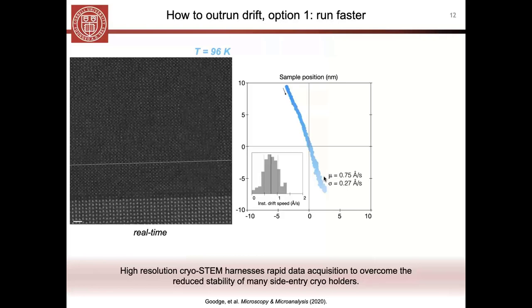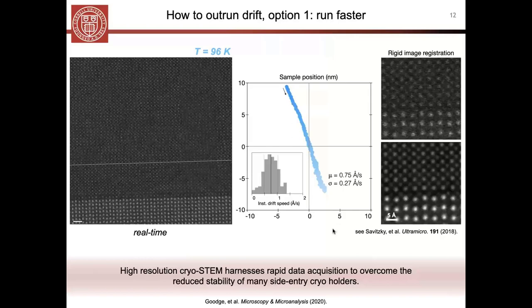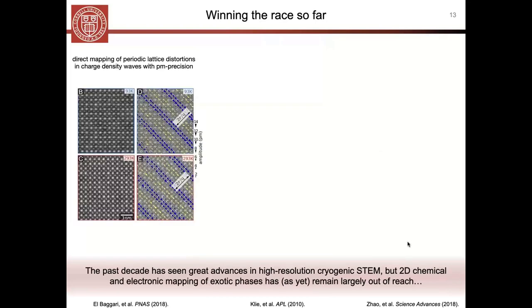Now, for relatively fast imaging techniques like, in particular, high resolution TEM or high resolution STEM, one way around this drift is to acquire a series of very, very fast images, like a stack of fast acquisitions, and then sum them together to produce a high signal to noise average that has overcome those position differences as a function of drift. Using these kinds of techniques, there's been a lot of really successful cryo-STEM and cryo-EELS done already.